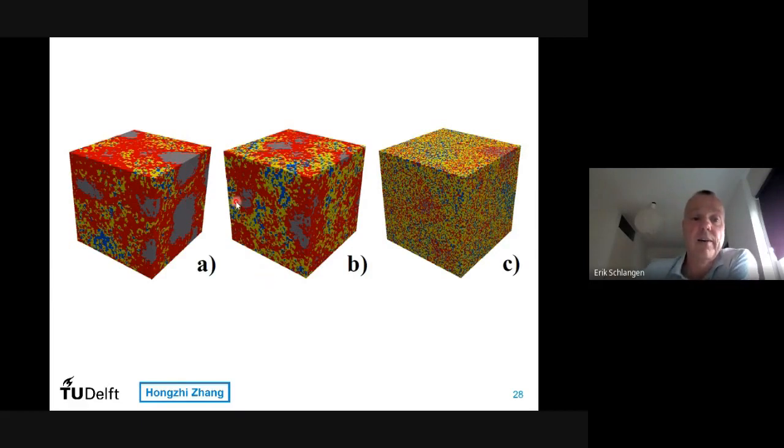And you see, then you have similar microstructures that we had when we started with the HYMOSTRUC model, where you start modeling spherical cement particles, do the reaction of the cement and the water, and you get formation of your microstructure. So you get similar images then by scanning it, but of course we know that our cement particles are not spherical, but they are irregular of shape. So this is more closer to reality if you do it in this way, if you do it with the scanning and get your microstructure from there.